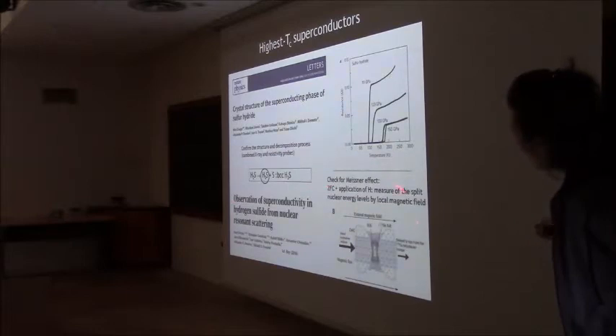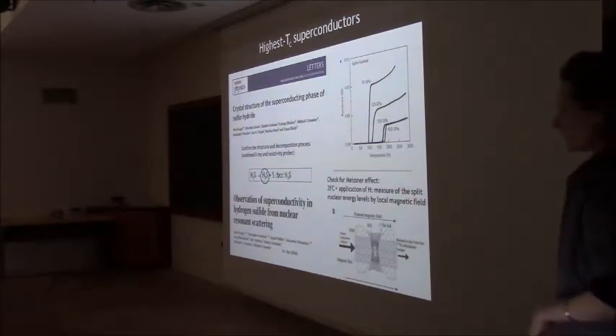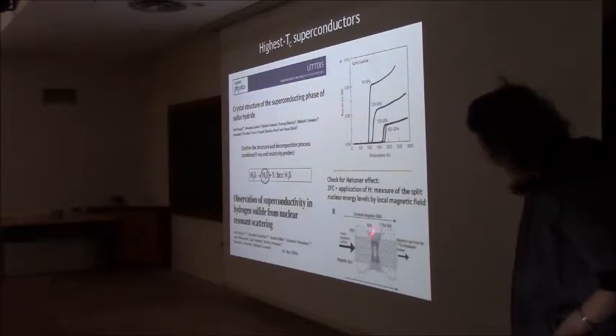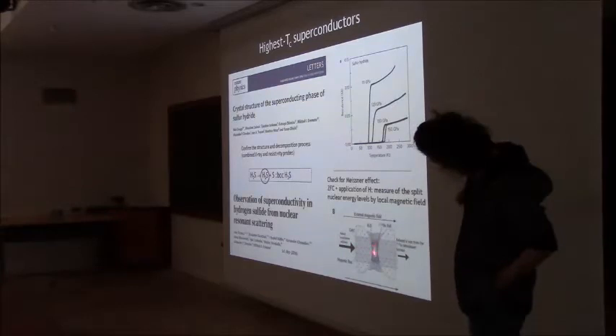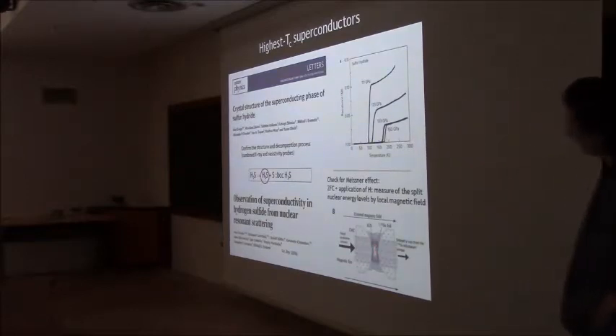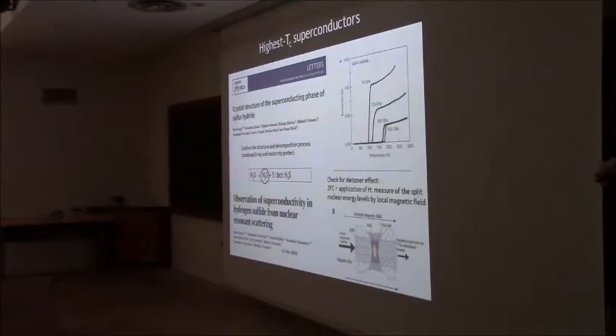And more recently, they also checked the Meissner effect using a very different technique. So this is the gasket, this is the diamond, and here you have the hydrogen sulfide. And inside they put a very small foil of tin, and they measure the splitting of the nuclear energy level of this tin, which is of course related to the local magnetic field seen by the foil. And depending on the temperature, when you cross the superconducting transition, your hydrogen sulfide will shield the magnetic field or will let it enter. So with the difference, you see the change of the splitting, and somehow you check the Meissner effect.